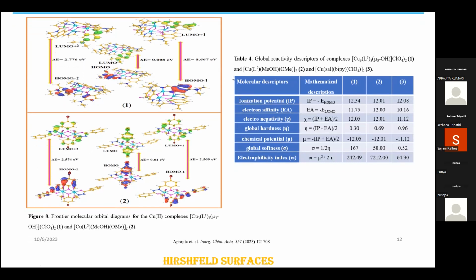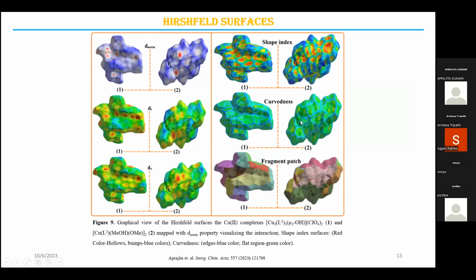Next, we have studied the Hirshfeld surface analysis, which tells us about the different interactions within the crystal system. Talking about the Hirshfeld surface d norm, the red dots show the strong interactions such as hydrogen bonding. The whiter patches show the weaker interactions, while the blue shows the absence of interactions. Also, through the shape index, we can conclude about interactions such as pi-pi interactions and CH-pi interactions through the triangular blue and red regions.